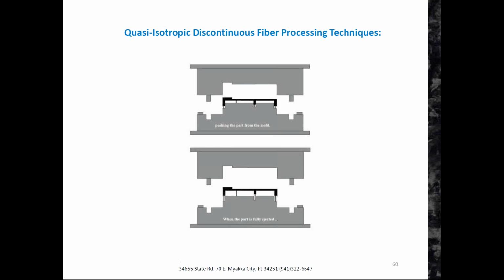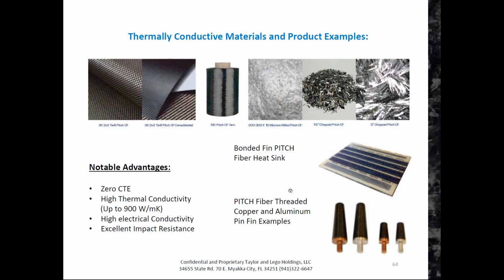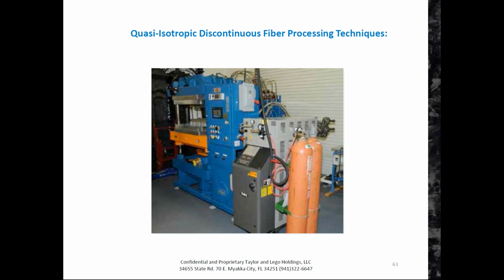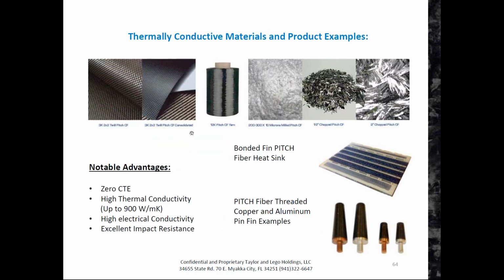The thermoplastic tooling can potentially be even a little less, but the geometry is a little more constrained. It wants to be more of a continuous thickness, and you accomplish the variations in thickness with ancillary components. This right here is one of our presses that is 225-ton capability. It's a 28,000-pound press, and this is a 36 kW oil heater next to it. We oil heat the platens. The molds are very simple. They're straight pull. They're aluminum, so they're reasonably inexpensive. We produce them all in-house.